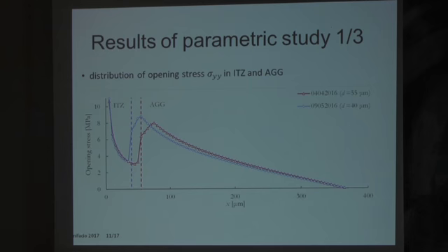So there are some results of our study. There is a distribution of opening stress between the interface through the ITZ and aggregate. The dashed lines are the interface between these two phases. For the first composite the thickness of the ITZ is 55 micrometers, for the second it is 40 micrometers.